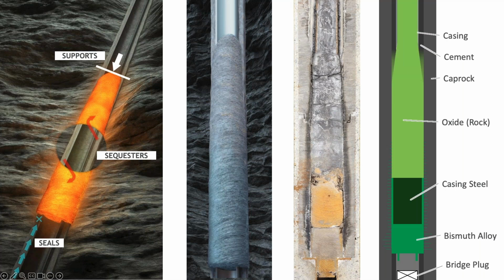From the bottom moving upward, the bottom is the seal phase, consisting of bismuth alloy that we create as a result of our reaction. It provides a seal across the full wellbore cross section, and makes up the bottom of the barrier. The middle portion of the barrier is the sequester, the melted casing and metals that form the center portion. They are in fact encapsulated by the bismuth alloy sealing material. And lastly, the upper portion of the barrier is the support section, which is oxide, artificial rock, if you will, which provides the anchor support and mechanical support, holding that barrier in place during the reaction process.